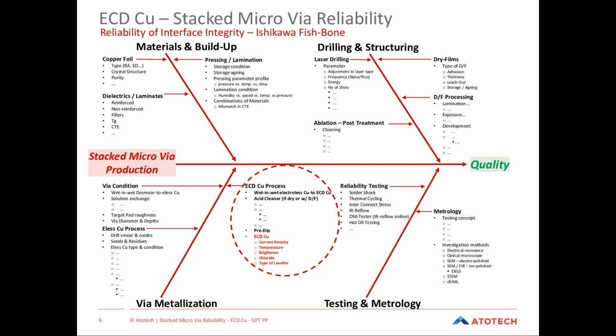And that was one reason to choose another example, which is also more impressive in my opinion, because to see that copper and nickel can have a perfect epitaxy if the interface is clean should convince you that this is even more likely than for copper-copper adhesion, for copper-copper build-up. So I'm sorry that I was not able, and it was not allowed for me, to show you real production samples from stacked microvia build-ups during this webinar. But at the end, I thought this kind of imaging and example is also impressive. But you will find the same interface problems. You will find the same elemental analysis between copper and copper deposits. So there is no difference. This is at least what I can promise here.